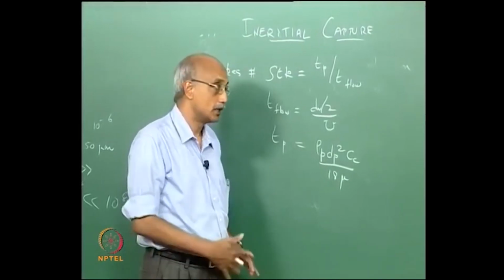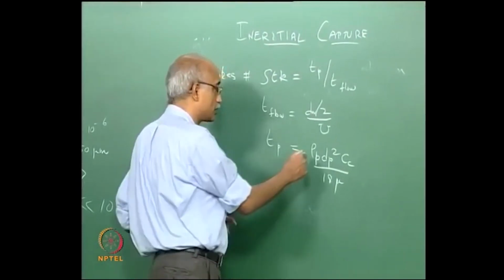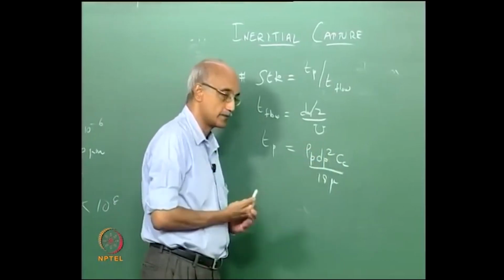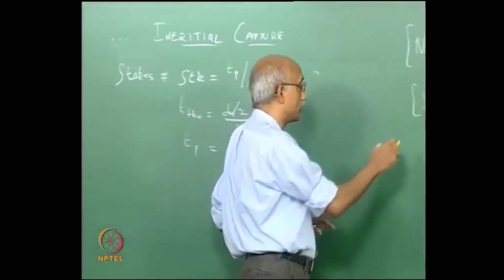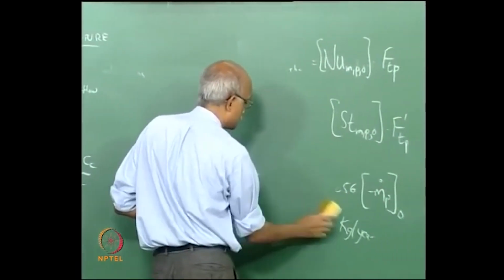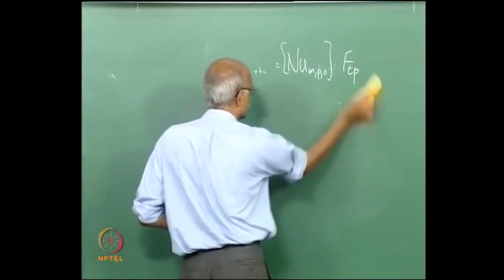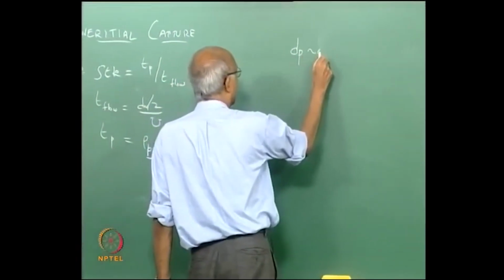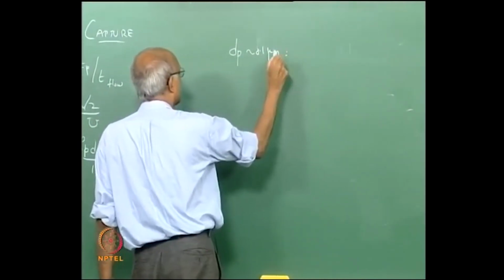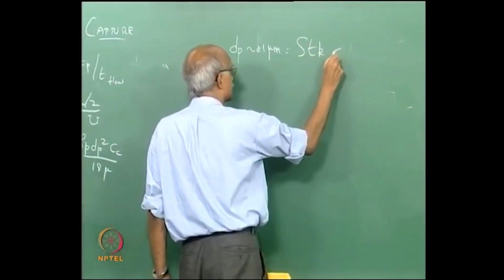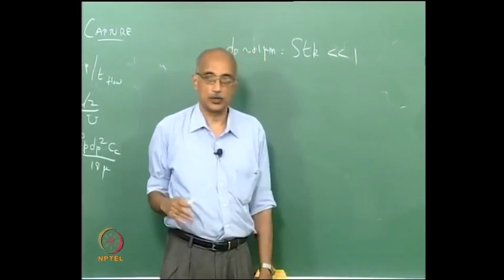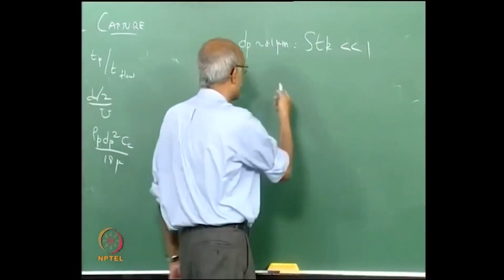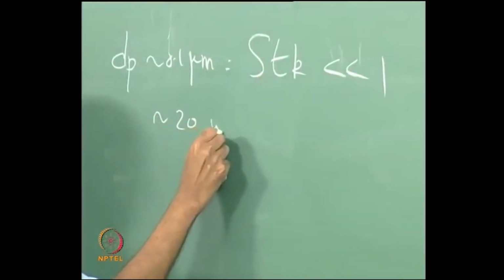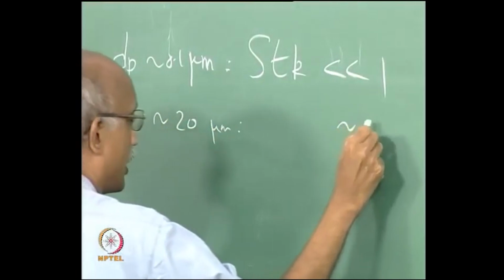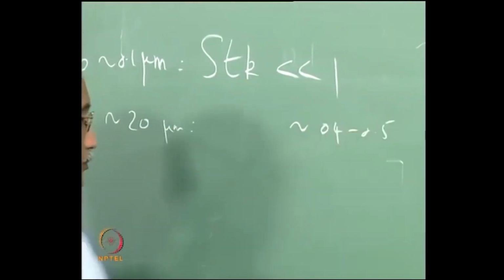Now, if you actually substitute values for all these parameters and estimate Stokes number for different particle sizes, what you will find is for particles that are of the order of 0.1 microns, submicron, Stokes number is actually well below 1, of the order of 0.0 something, whereas for particles of the order of 20 microns, Stokes number is approximately 0.4 to 0.5.